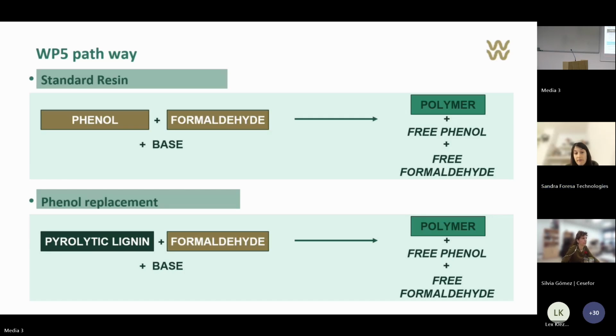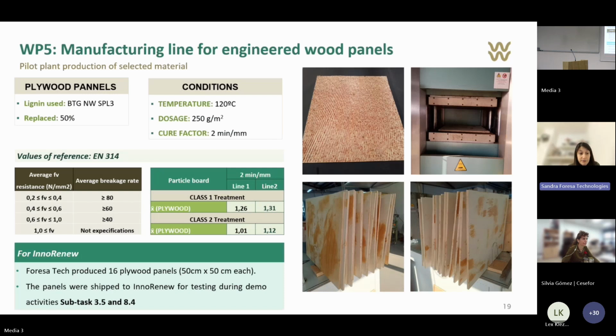In our pilot plant, we successfully manufactured plywood panels using a resin where 50% of phenol was replaced by pyrolytic lignin, called SPL3. The results were quite good because the panels successfully meet both Class 1 and Class 2 treatment standards, as you can see in the table. This was the best resin obtained for the plywood panels.